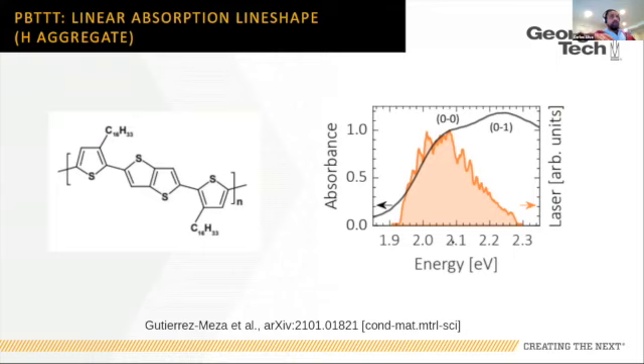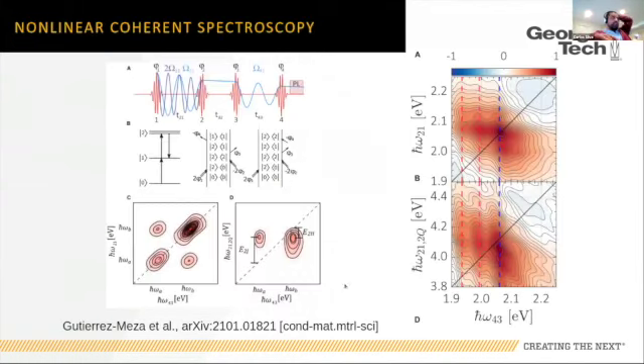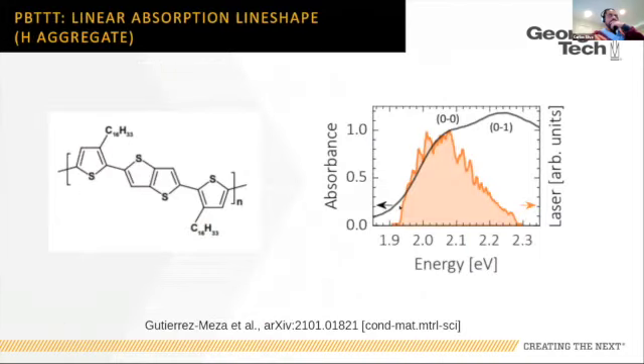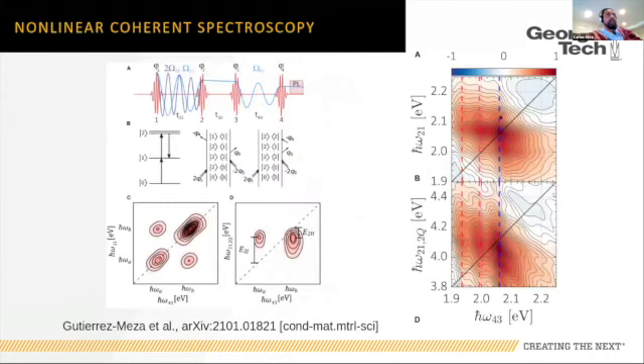But it looks like P3HT. If I look at the absorption spectrum, I see a suppressed 0,0 compared to 0,1. This looks like an H aggregate. And so this is kind of like P3HT. So here's the picture that I had. Here's the data. Now, the way my laser spectrum is tuned, I wanted to cover all of the 0,0 line, and I'm slightly overlapping into 0,1, but I need to cover all of the 0,0 line for a reason that you'll see in a minute. And so what I see here, this peak here, is this diagonal peak. This is a one-quantum 2D spectrum. This diagonal peak is the peak of 0,0, okay?